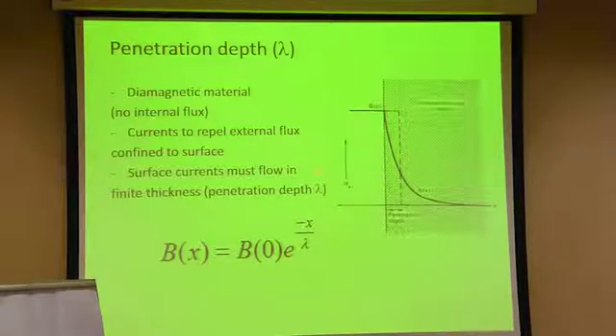Because these currents must flow in a finite thickness, the currents are going like this. So deep inside the superconductor we do not have any current, but at the surface we have a current which creates a magnetic field which opposes the applied one. The magnetic field decreases from the external magnetic field at the surface, B at surface at x equals 0, to 0 inside, because we have seen that inside the material we have 0 internal field. The distance at which B of 0 decreases by the Euler number, e, is called the penetration depth.